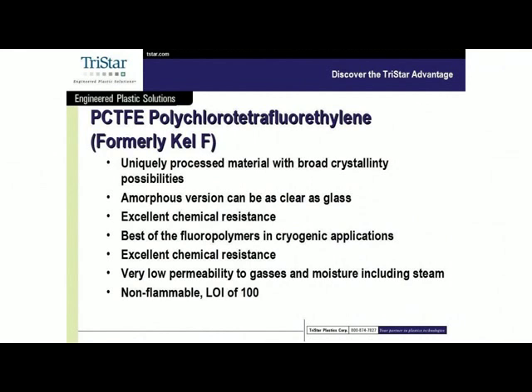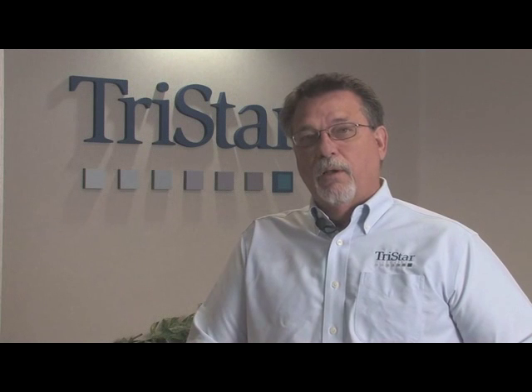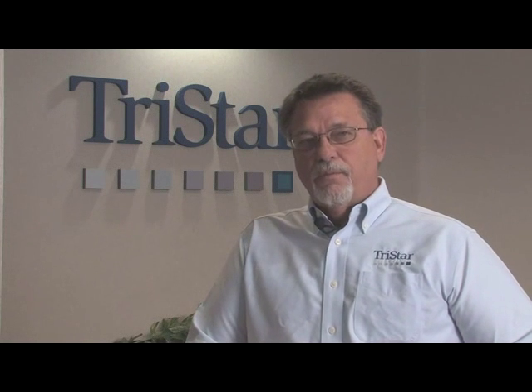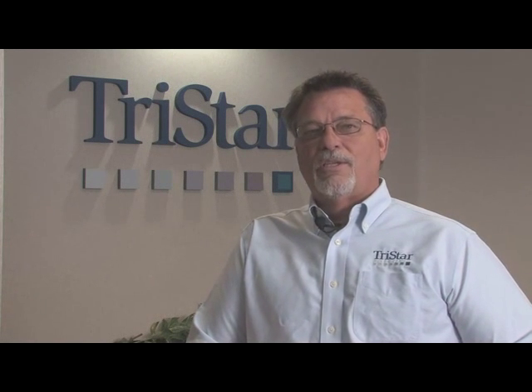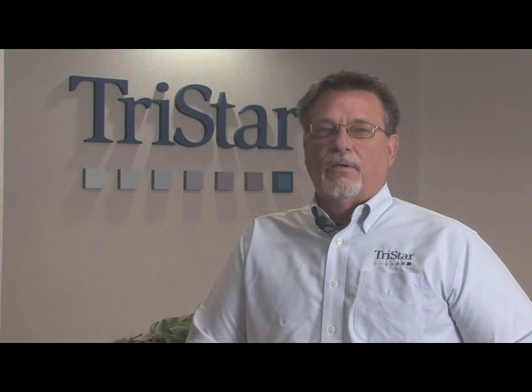PCTFE has very good chemical resistance. In cryogenic applications, it is the go-to material, especially for valve seats. Probably the number one material for liquid oxygen, liquid nitrogen, any place where there's a continuous cold temperature exposure. And the nice thing is that as a valve seat material in those conditions, again, it will not embrittle, and you still have enough flex property in it that it will continue to seat as a ball seat or a diaphragm seat or something like that.